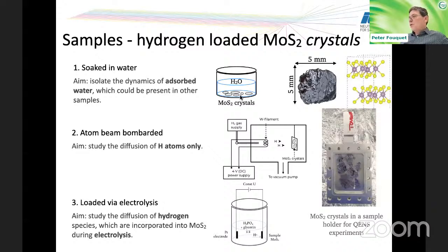So what we did is, first of all, we looked at very specific samples. We looked at molybdenum sulfide single crystals. You can see them here just as a general image, and here you see them put in a sample holder. It's a flat aluminum cell, the inner part is about 2 by 3 centimeters. And we looked at different kinds of sample preparations. Once we soaked them just in water without any chemistry attached. We atom bombarded the single crystals, and we loaded them via electrolysis.